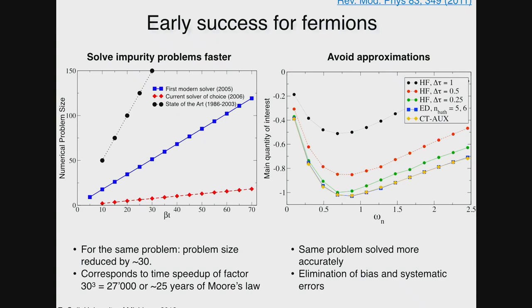And that means that because these are matrix operations that we have here, they go with the matrix size cubed, the linear size cubed, it corresponds to a speed up of about 30 cubed or 27,000. Or if you think in Moore's law, it's about 25 years of Moore's law in just time to solution that we have with these diagrammatic expansions as compared to simple Trotter-Suzuki based methods.